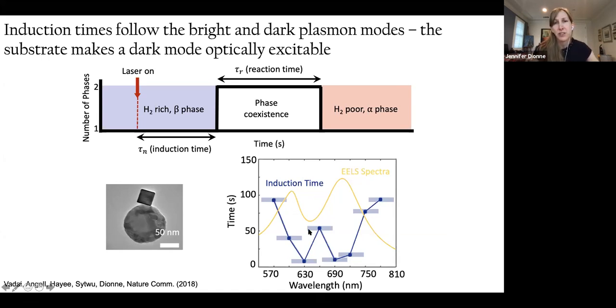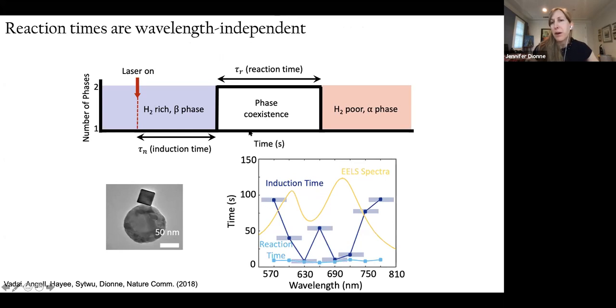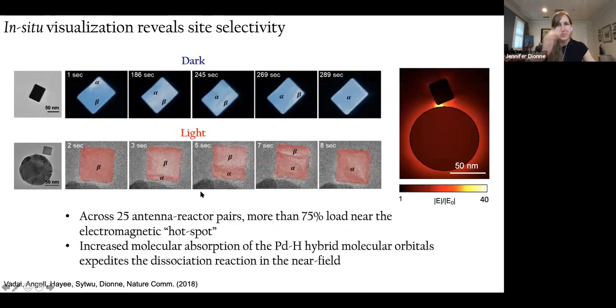Okay, so we have 10x increased induction times. What about the reaction times? You can see that the reaction times also kind of show some dips corresponding with the plasmon resonances, but by and large, they're wavelength independent. And that's because the induction time influences how the hydrogen is catalytically splitting at the surface, whereas the reaction time is really going to be determined by how the hydrogen is diffusing within the nanoparticle.